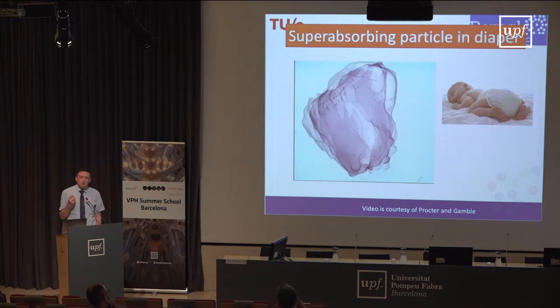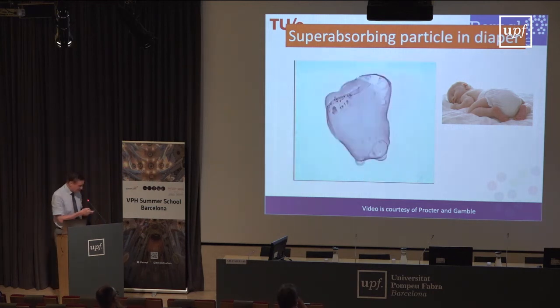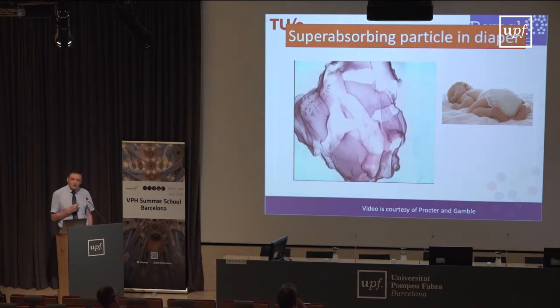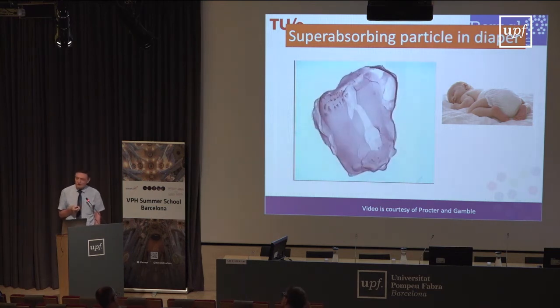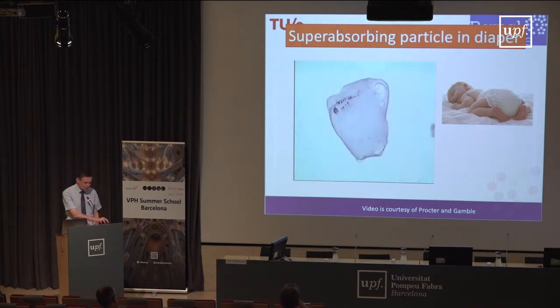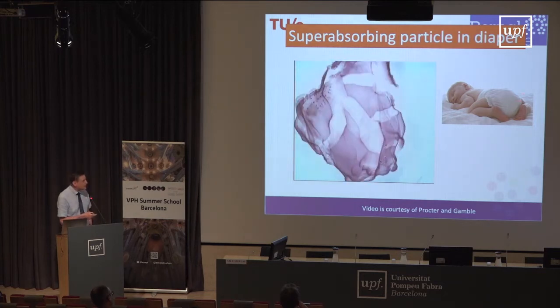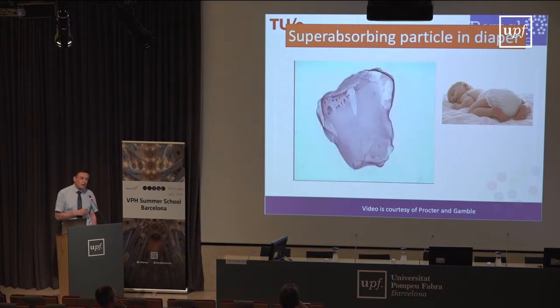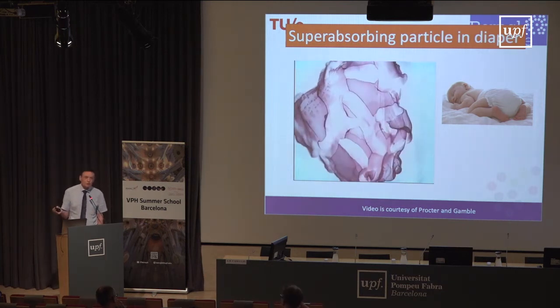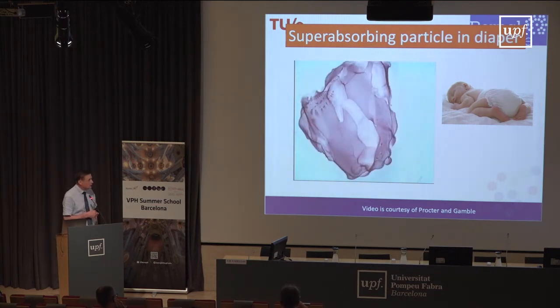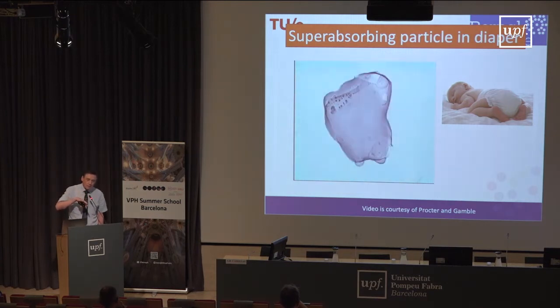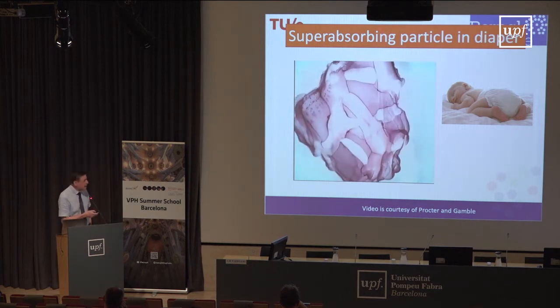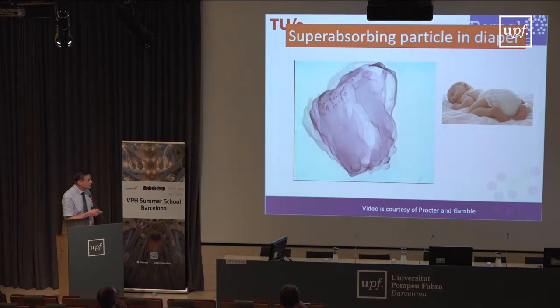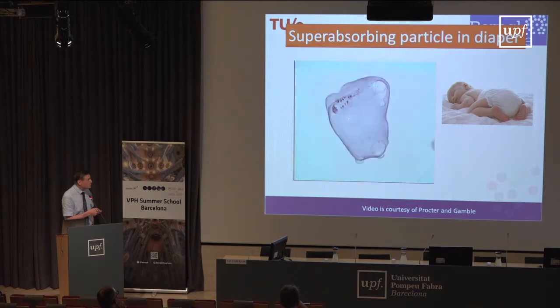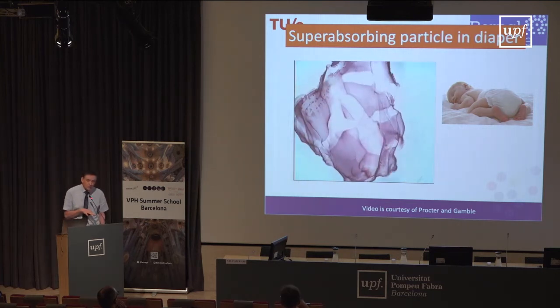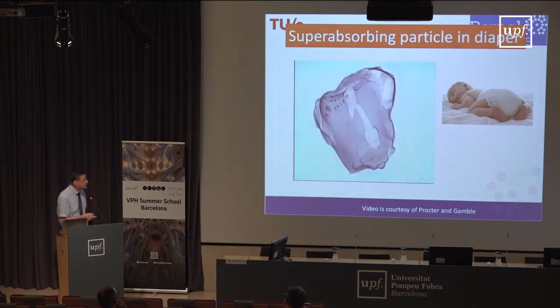What you can do is use applications from the industry. And now a very famous application, which we all know, is diapers. Diapers are highly swelling. A very efficient product, which all of you who have had children had used a lot. And if you go down to what happens inside the diaper, you find small beads of hydrogel, which swell about 30 times their own volume. And they are actually surrounded by a cross-linked layer on the outside. And you see, as it is swelling, and this is actually a bead of this type inside the diaper, when it is faced with a gush of urine, it starts swelling. But before swelling, it has to get this surface shell to crack. And it cracks into pieces.